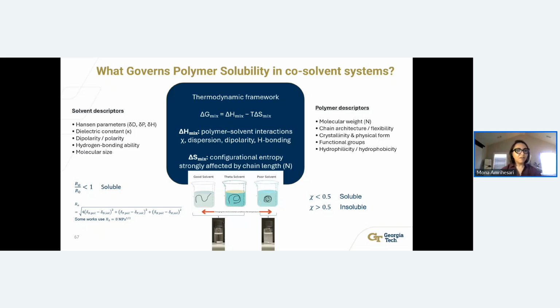We have a very good literature and deep knowledge on the Hansen parameters, which offers 3 different variables: the dispersion, polarity, and hydrogen bonding. We know now, based on the literature, that dielectric constant is another parameter that's affecting the co-solvent system. We also know the Flory-Huggins interaction parameters in the solvent system. It's very important: when the polymer and solvent have an interaction parameter below 0.5, it means that it's soluble, and if it's above that, it's insoluble.